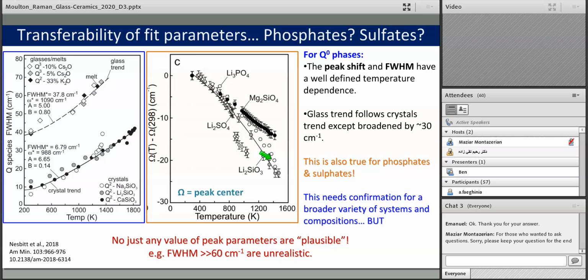And ultimately, at the end of the day, if you see fits with full width half max very, very large, a full width half max larger than 60 would be up here, a glass at a very high temperature, 1400 degrees Kelvin. And so fits with full width half maxes very large are probably unrealistic, or the vibration is not the same stretching vibration that we see in these crystal phases.